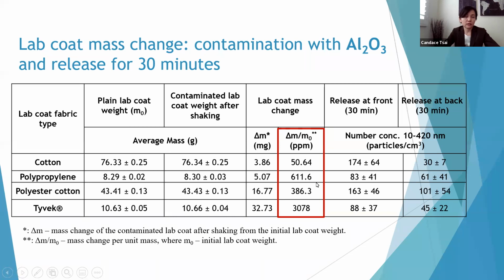Why is that? It's because the surface actually has a very similar amount of nanoparticle deposited onto the surface, because we aerosolized particles under a very similar level of concentration.